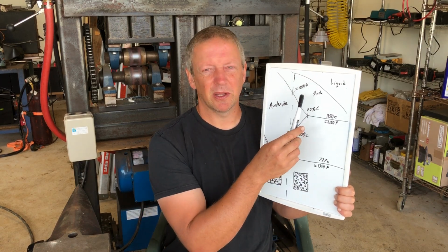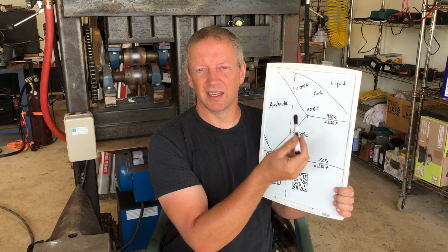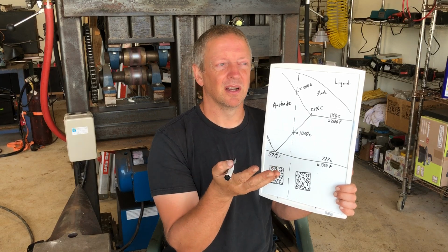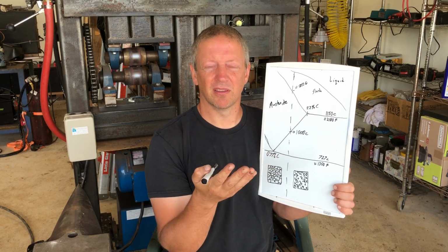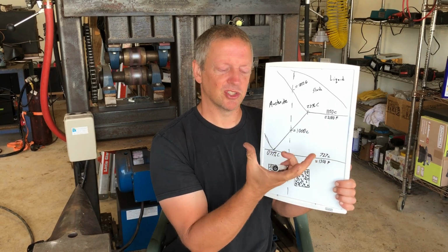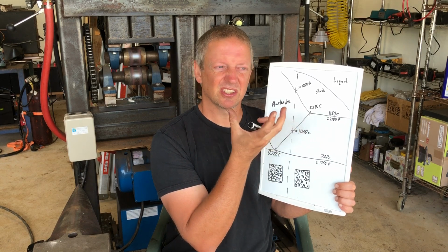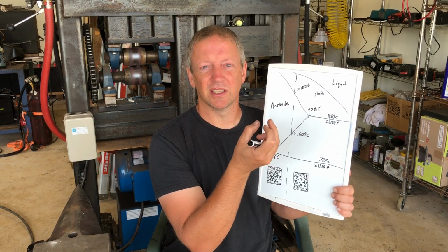And when I've talked about this before, that when an ingot solidifies, you end up with microscopic pores because liquid is larger than solid. So if you imagine your ingot has solidified first on the outside and set your volume, but now your material inside is shrinking, you're going to have some voids in there no matter what.